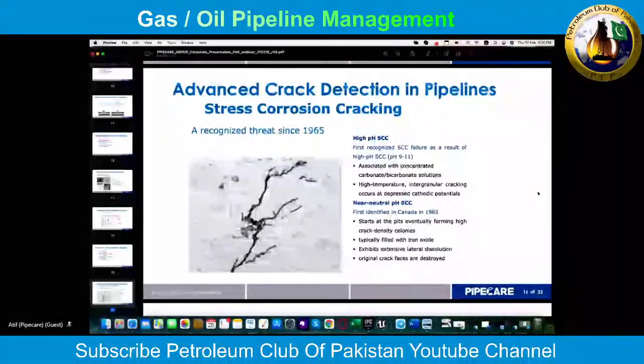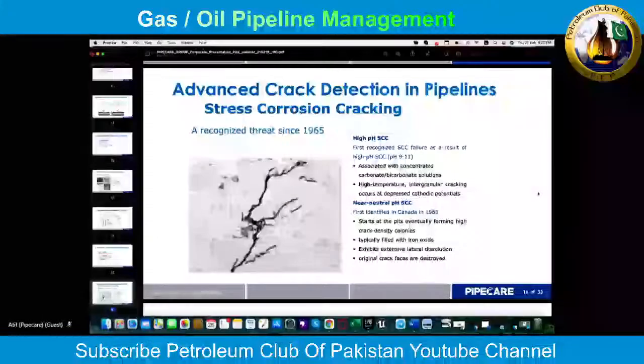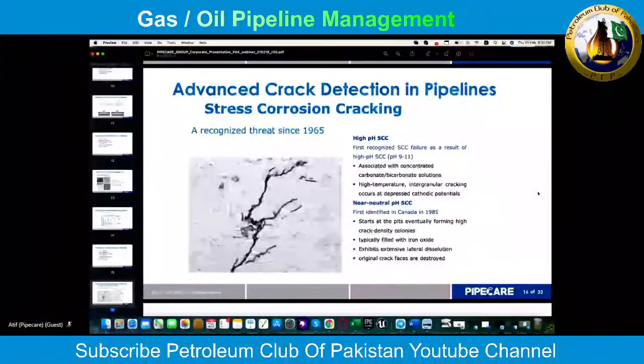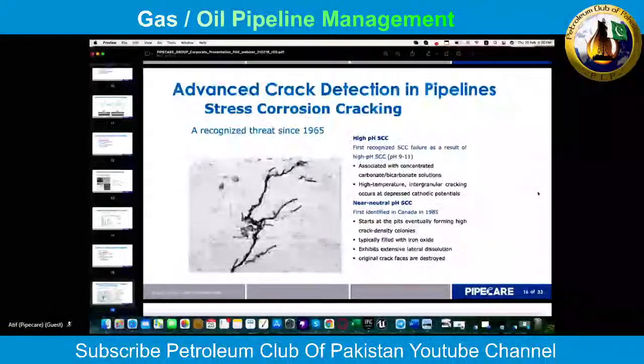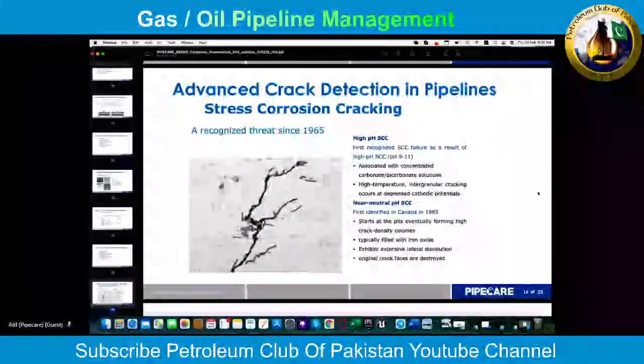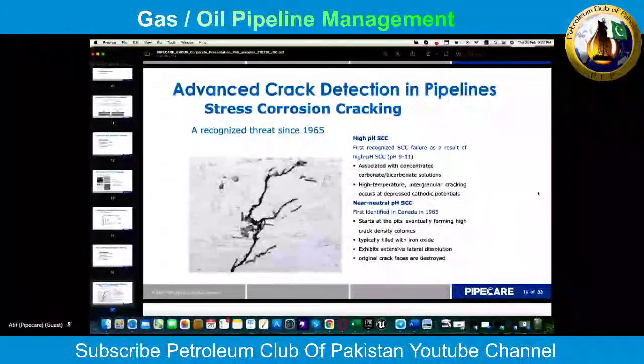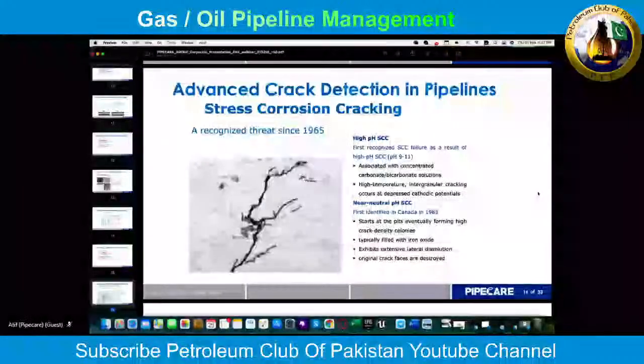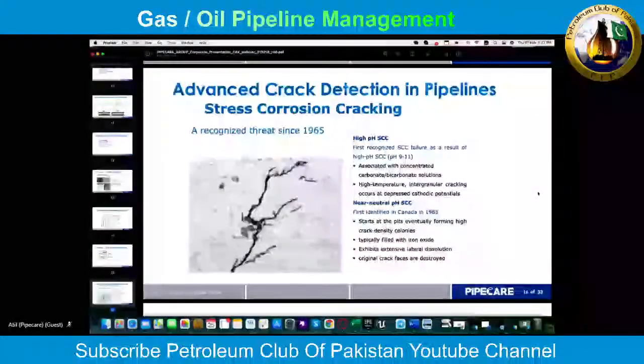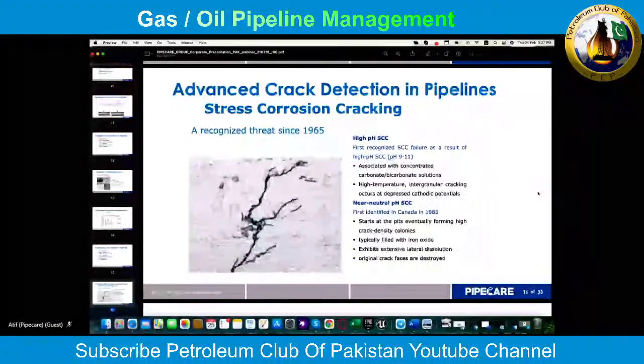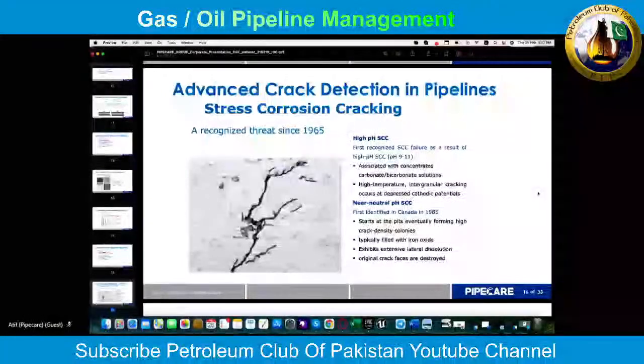Again, the parameters are the same. It's high temperature, it's pressure fluctuations, it's a lack in coating, and the result is the same, but small pits are building which grow to cracks, to crack colonies, and once this crack colony reaches a critical size, it very, very quickly bursts and creates a leak or a rupture. Next, please.